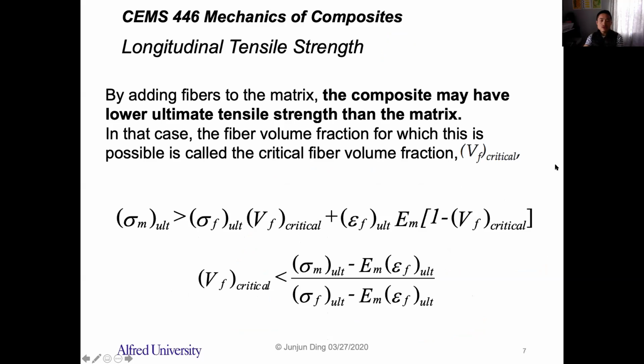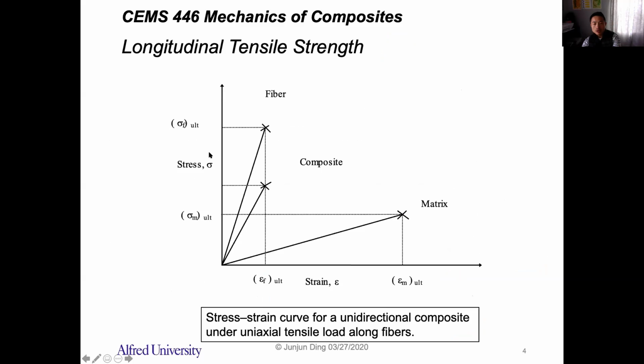Okay, so if you add fibers to the matrix, the composite may have a lower ultimate tensile strength than the matrix. What does that mean? So if you add in, let's go back to this figure, right? We calculated, we know the ultimate strength of the composite will be calculated based on the ultimate strength of the fiber and also the strength of the matrix at this time, right? So this is calculated based on the volume fraction of the fiber times the volume fraction of the matrix. If you have a really small volume fraction of the fiber, you may have